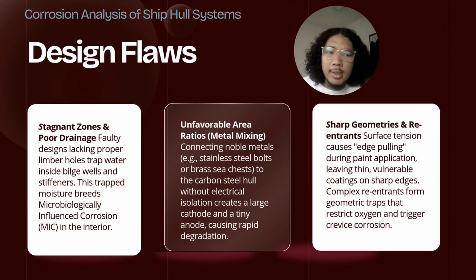Structural design flaws can be a ship's worst enemy. Stagnant zones and poor drainage in bilge wells and ballast tanks trap water without proper drainage holes. This trapped water breeds microbially influenced corrosion from the inside out. Unfavorable area ratio or poor metal mixing is a disastrous flaw. Securing a brass sea chest directly to carbon steel guarantees the surrounding steel will rapidly degrade. Finally, sharp geometries create weak points in the paint coating due to surface tension, while deep structural pockets create crevices that restrict oxygen, directly causing crevice corrosion.